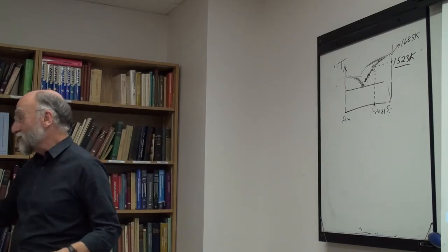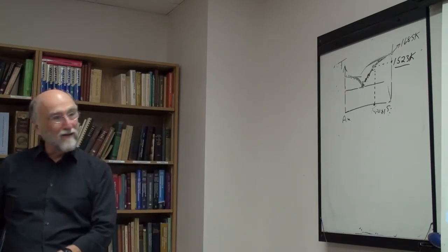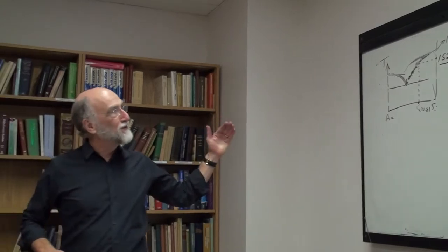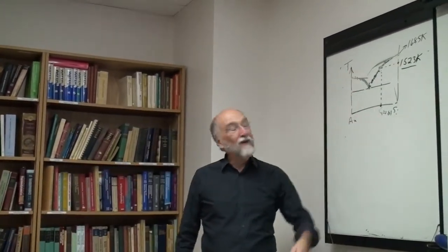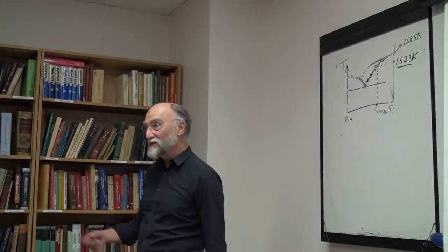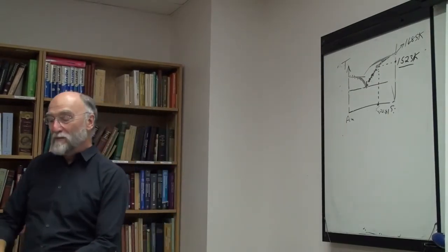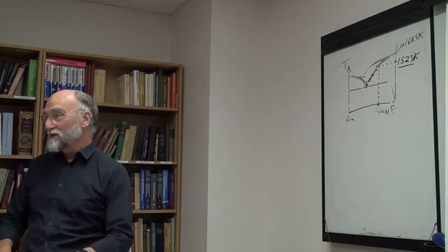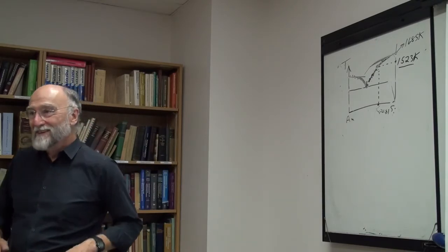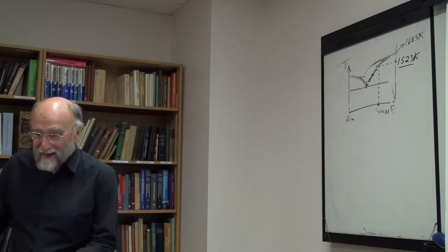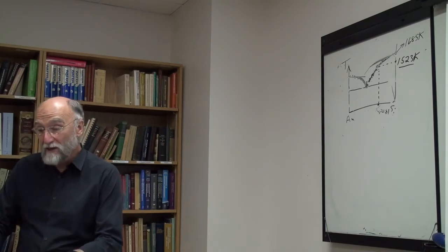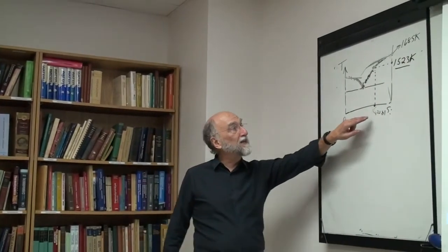I went into the phase diagram book, and I found that these phase diagrams just were beautiful, because the limiting slope was exactly what you predicted from the heat of fusion, and everything was fine. And this showed absolutely no solid solubility. But when I looked at who got the heat of fusion, they had used this technique. So that proved nothing. Actually, quite a few high melting measurements, high melting metals and so on, are done this way. So that's the way to check it then.